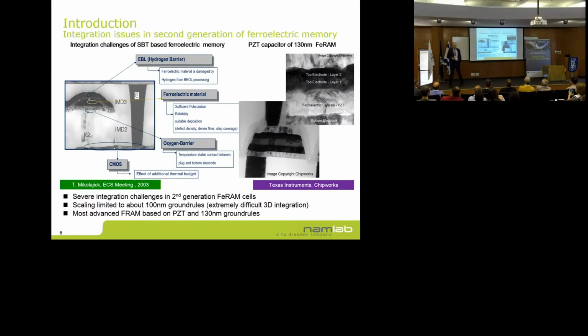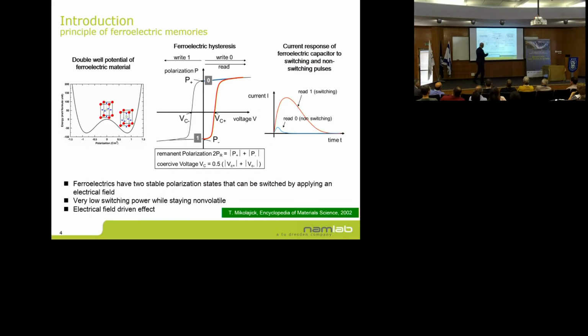Nevertheless, it's failing to scale down as fast as other memories. The reason is simply that the materials you use here are very, very complicated. They are normally perovskites, or in some cases even layered perovskites, and on the one side you need a high thermal budget to even bring them into the crystal structure you need. Once you have this crystal structure, it's very sensitive to things like hydrogen or other attacks. So you have to do a lot of things in the process to achieve a result, as you can see in the devices that you can buy from Texas Instruments today.